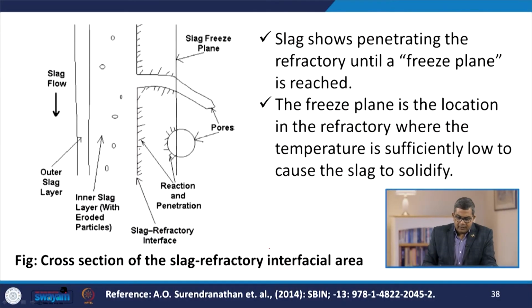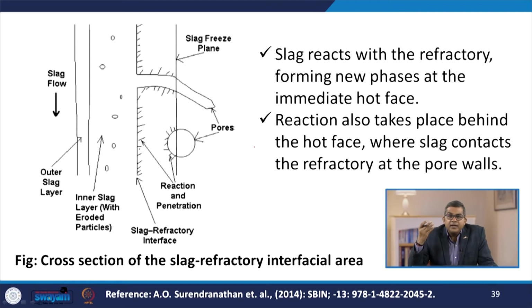Now, here you see the cross section of the slag refractory interfacial area. Now, the slag shows penetrating the refractory until the freeze plane is achieved. Now, the freeze plane is the location in the refractory where the temperature is sufficiently low to cause the slag to solidify. Now, slag reacts with the refractory, forming new phases at the immediate hot face. Now, reactions may also take place behind the hot face where the slag contacts the refractory at the pore walls.